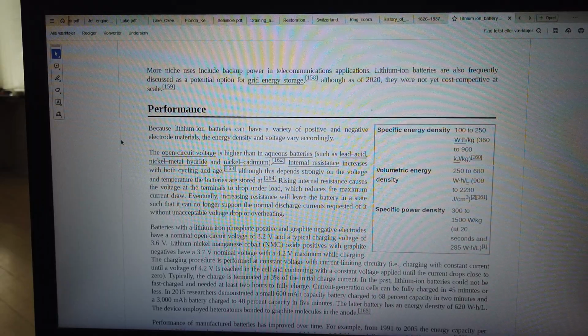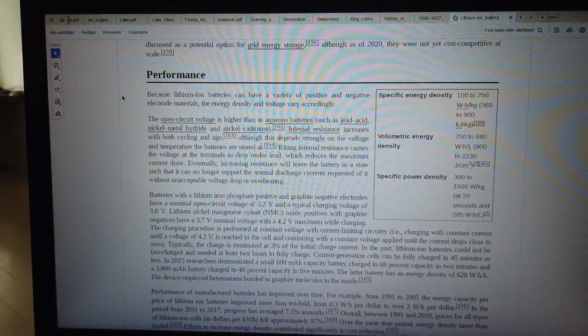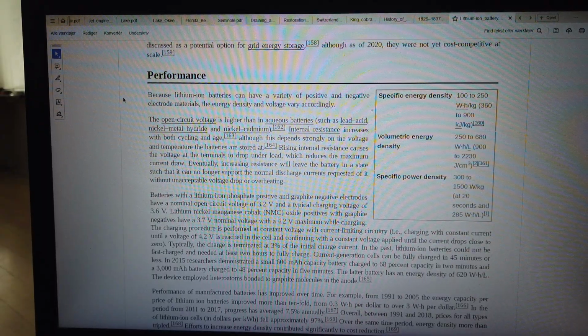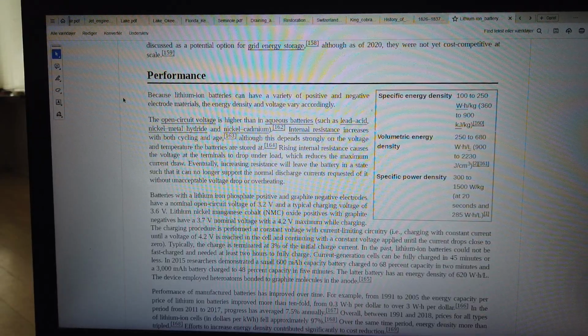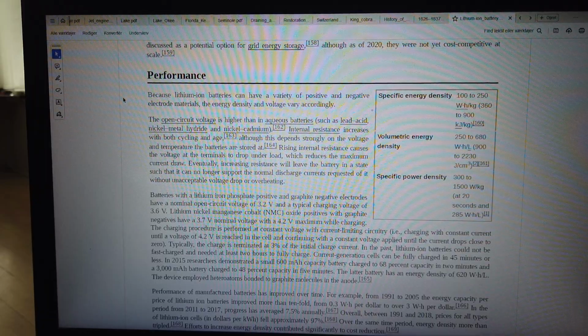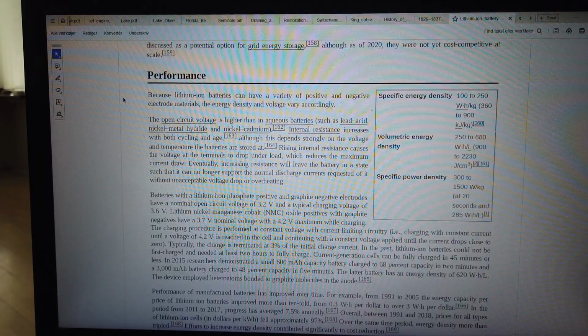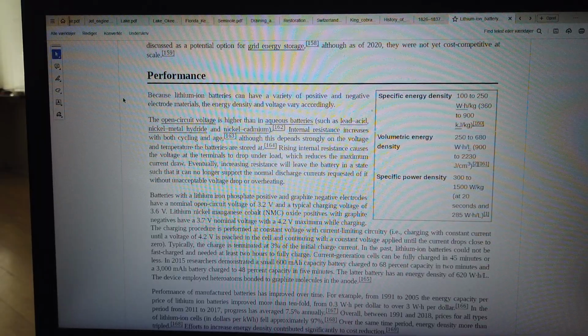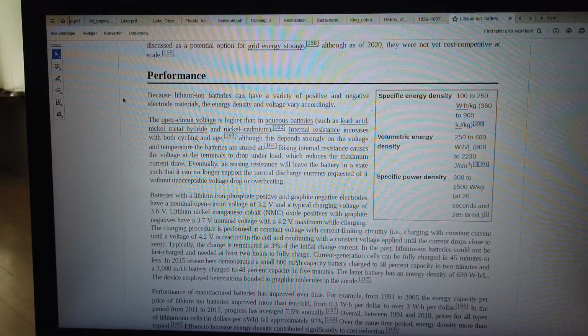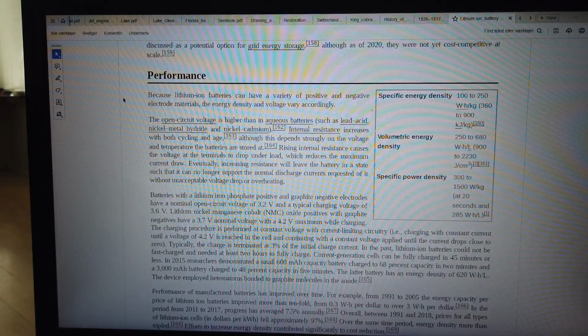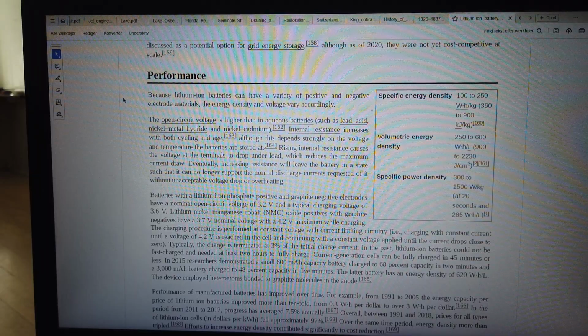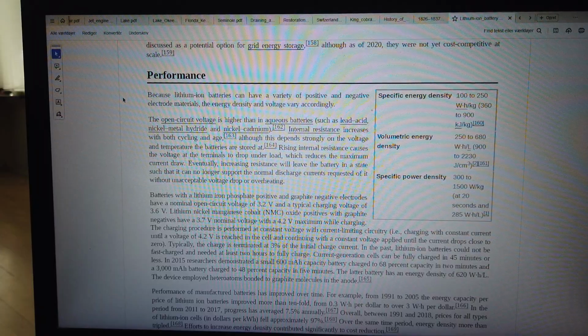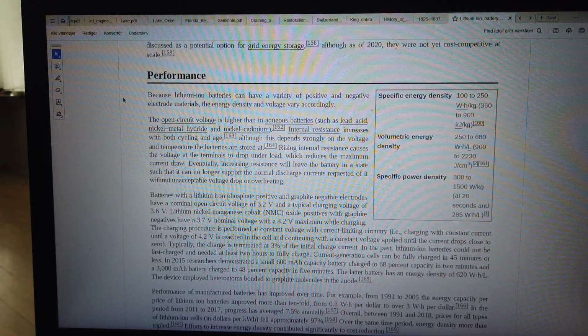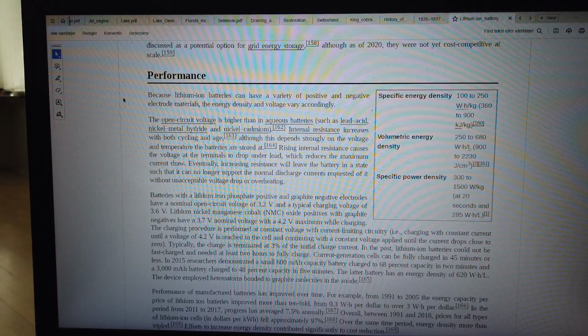Performance. Specific energy density: 100 to 250 W·h/kg, 360 to 900 kJ/kg. Volumetric energy density: 250 to 680 W·h/L, 900 to 2230 J/cm³. Specific power density: 300 to 1500 W/kg at 20 seconds and 285 W·h/L.